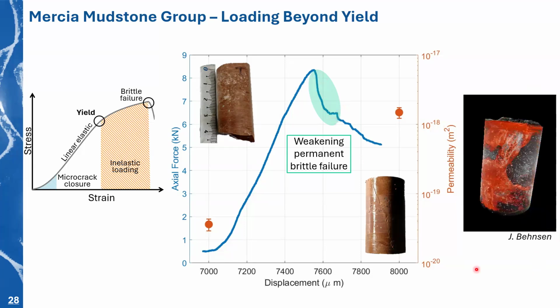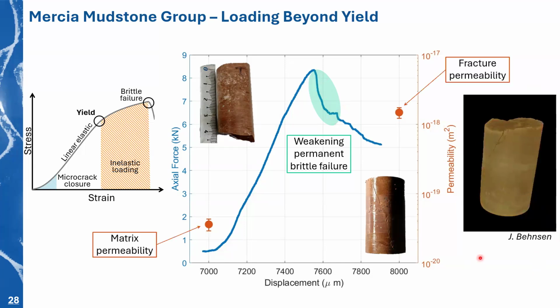So when it reached yield, this sample strengthened a little bit more, but then its strength dropped massively. So this is when it broke into multiple fractured sections. So we have permanent brittle failure here. So before it failed, we had quite a low permeability. So that would have been for the matrix of this mudstone.